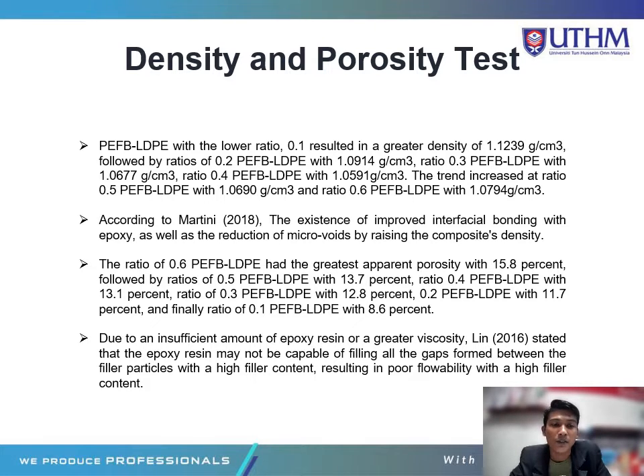The ratio 0.6 PEFB LDPE had the greatest apparent porosity with 15.8%, followed by ratio 0.5 with 13.7%, ratio 0.4 with 13.1%, ratio 0.3 with 12.8%, 0.2 with 11.7%, and finally ratio 0.1 with only 8.6%. Lin (2016) stated that due to an insufficient amount of epoxy resin and a greater viscosity, the epoxy resin may not be capable of filling all the gaps formed between the filler particles at a higher filler content, resulting in poor flowability.